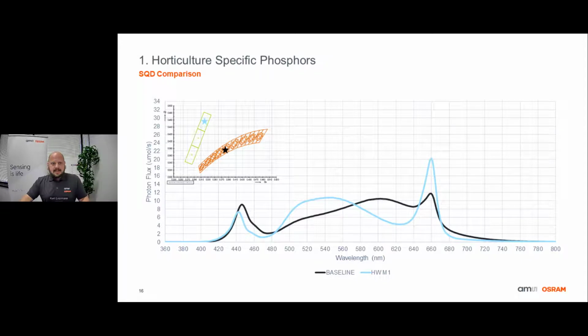You can clearly see how the red content between 600 nanometers and 640 nanometers has significantly been reduced and been replaced with more efficient direct emitting red LEDs between approximately 650 and 670 nanometers. The blue content was slightly reduced at the 450 nanometer peak, but there is now a little bit of additional blue between 490 and 500 nanometers. The green content between 500 and 560 nanometers has been significantly increased as well.